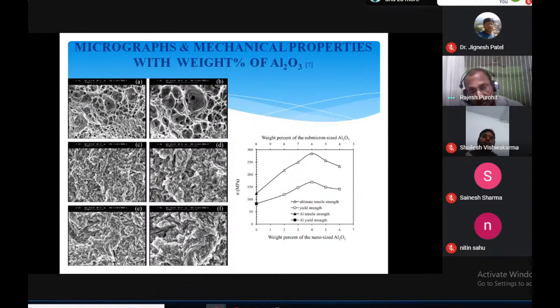The dark triangle and square show the values for pure aluminum tensile and yield strength. Pure aluminum has about 80 megapascal, and when we reinforce with nano aluminum oxide, the strength first goes on increasing, and at about 4 weight percent we have the highest yield strength and also the highest tensile strength. After that it decreases. And of course, tensile strength is higher than the yield strength.